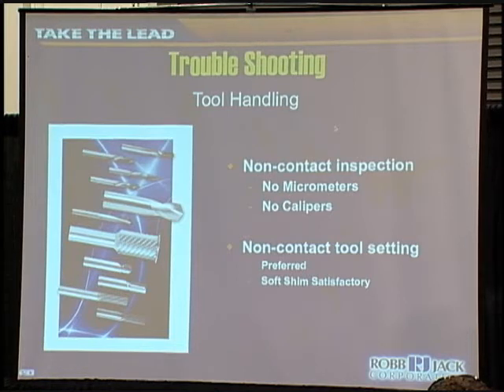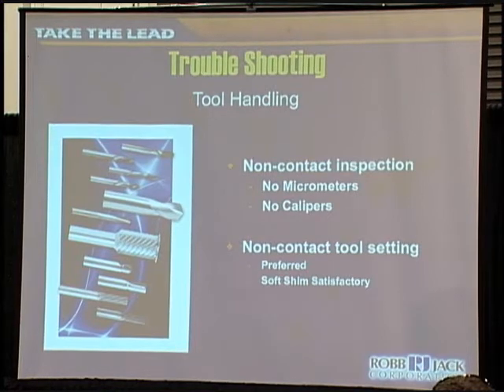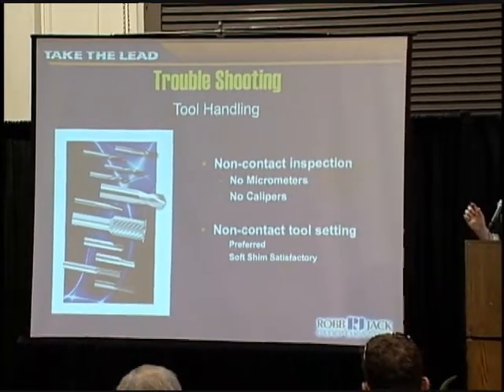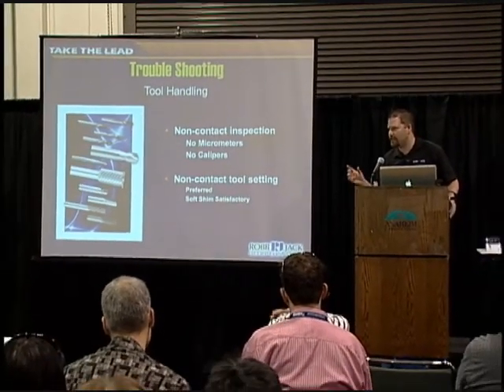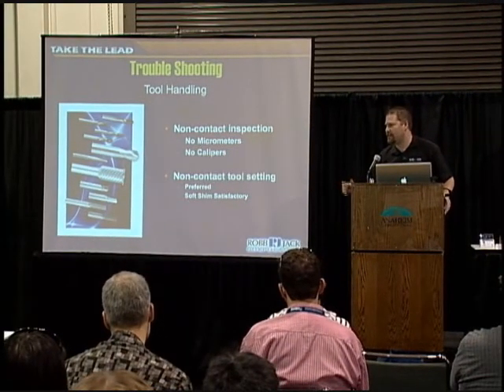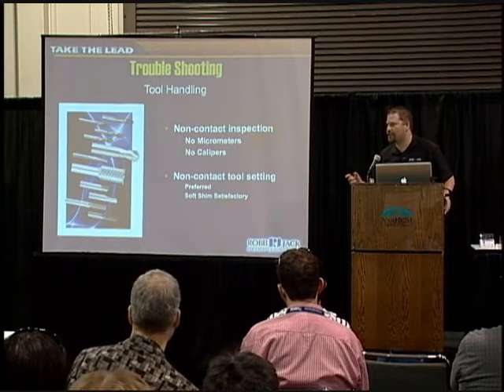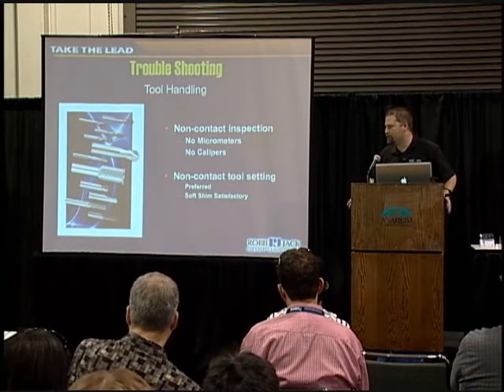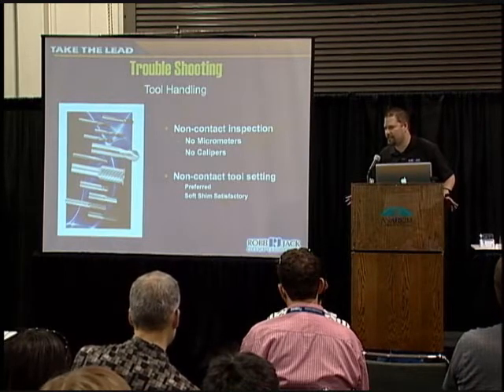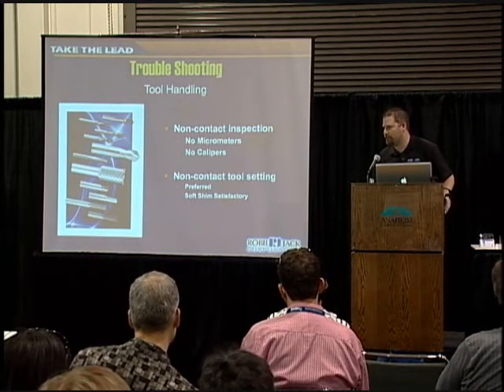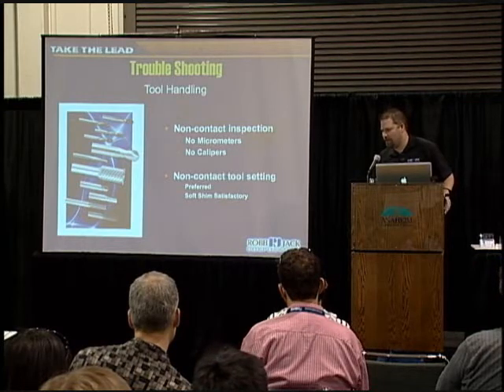Some of the other issues with the diamond coating and PCD is you want to use non-contact measurement. When you measure your tools, you can't use a micrometer, you can't use calipers or other type of contact measurement with the tool. You want to use any kind of vision system. We can give you inspection reports with the tools that tell you what diameter, what length of cut everything is, just so you don't have to measure it. You don't want to use any kind of contact measurement with the PCD or diamond. You'll probably chip it when you make a measurement with a hard surface.